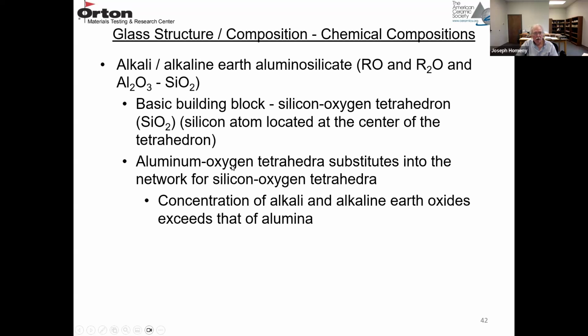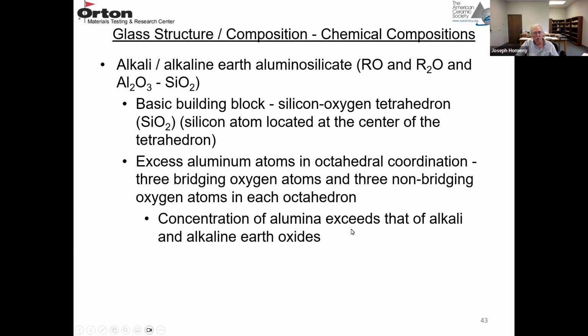So the aluminum oxygen tetrahedra substitutes into the network for a silicon oxygen tetrahedra. So this is the case if the concentration of the alkali and alkaline earth oxides exceeds that of alumina. So this would be for a small alumina content compared to the alkali and the alkaline earth oxides. So this is where alumina would be a glass intermediate. So the excess aluminum atoms are in octahedral coordination. 3 bridging oxygen atoms and 3 non-bridging oxygen atoms in each octahedron. So this is the second case.